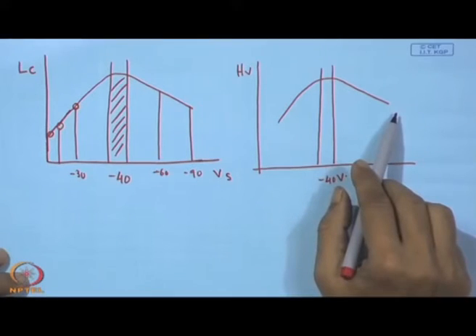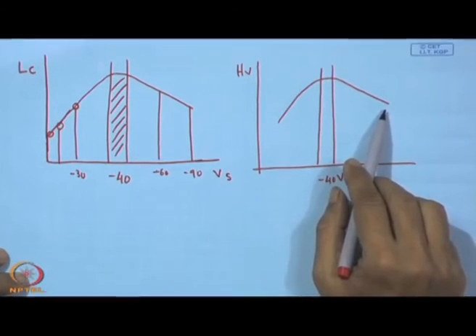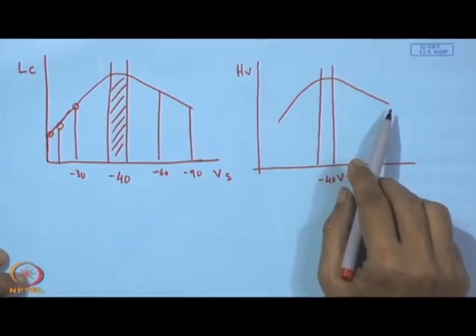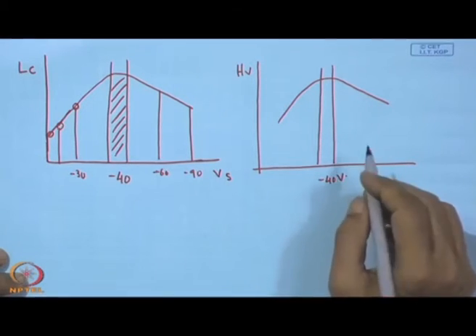However, if we go further to this, then what is happening is that too much compressive stress will be frozen inside the coating, and the material becomes too brittle on this side. When that indenter comes on this coating and tries to penetrate, instead of having any very localized plastic deformation, this loading of the indenter leads to crack propagation, because the material cannot undergo even the smallest possible plastic deformation, and as a result the material shows crack propagation, and that means it has a lower surface hardness.